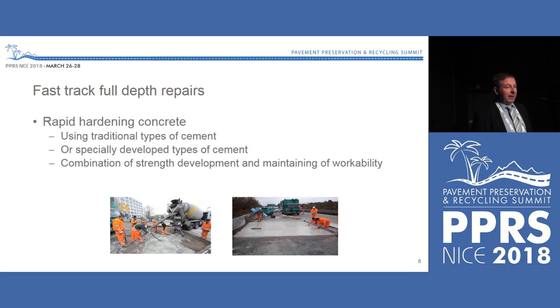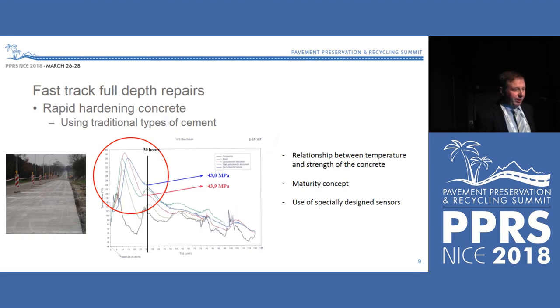If it has to go faster, and sometimes, no, first I'm going to show you this. It is a follow-up of this graph, shows you the follow-up of the temperature in the concrete. There is a relationship between temperature and strength, and you see here the strength that was obtained after 30 hours of hardening, and we got to something like 43 megapascal. Those were the values in small slabs on insulated and non-insulated, and we see that the real pavement is just in between. So this type of measurements allow us to predict the concrete strength. And now, thanks to the maturity concept, now special sensors have been designed in order to follow the temperature evolution and to predict the strength at a given moment.